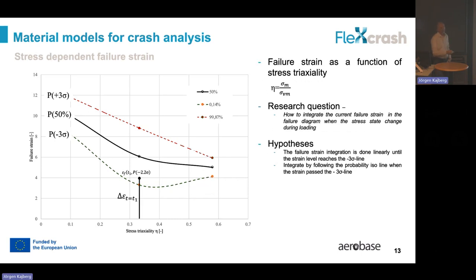The other condition is that when we deform more in the first step, so we pass this -3 sigma line, then we are in the world of probability. So we need to take care of that in another way. What we do then is that we follow the isoline. When we change the stress triaxiality, we start with the same probability in the next step before we take that additional strain step. So that's the hypothesis, and that's something we need to prove in this project.